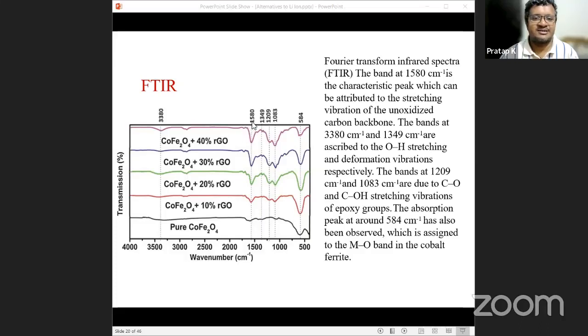So we have obtained the 1580 characteristic peak. This is the characteristic peak which can be attributed to the carbon backbone. So whenever we have a 1580 peak, then we can say that there is a carbon composition in it. Then you can look at it clearly. This 1580 peak intensity is increasing, and this shows that the amount of RGO that is present in it is also increasing. So the other bands, 3380 and 1349, this is 3380 and this is 1349. So these are attributed toward the OH stretchings.